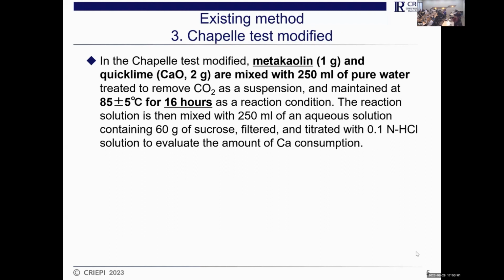And the third one is like this, the modified Chapelle test. In this case, it was used in France, I remember that. And they use metakaolin in the concrete admixtures. And this is not fly ash. Metakaolin has much higher reactivity than fly ash. And in that case, they mix 1 gram of metakaolin and quicklime, meaning CaO, like a free lime, 2 grams, and mix it into 250 milliliters of pure water. And the reacting condition is 85 centigrade, keeping it for 16 hours. And we need to estimate the consumption rate of the calcium ion.